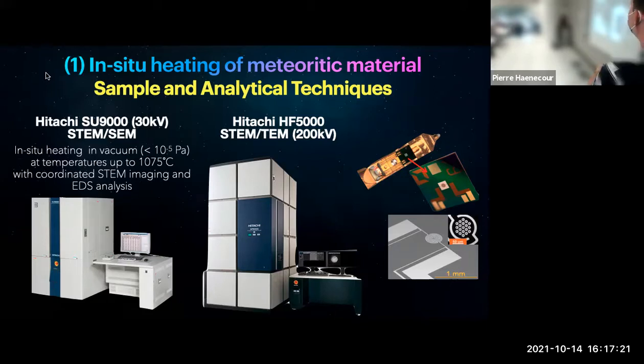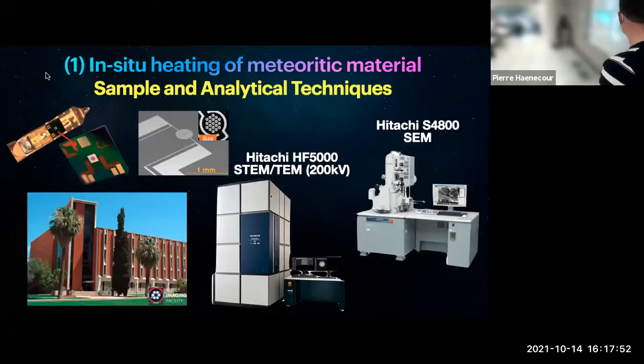And we did that in two different instruments. The first one was a low acceleration voltage hybrid STEM SEM. So it's basically a hybrid between a traditional SEM that you must be familiar with and a STEM. So it allows us to do both transmission and typical SEM imaging. And then we also did additional experiments using the Hitachi HF5000 here in the basement of Kuiper. It's a STEM TEM 200 kV instrument.